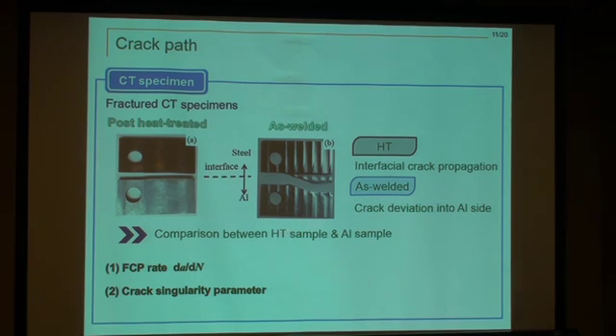This is the appearance of the crack path. As I have explained, in the as-welded joint, the crack didn't propagate along the interface. It deviated into the aluminum side because the aluminum side is softened by the heat generation from the friction. And after the post-heat treatment, the crack propagated along the interface.